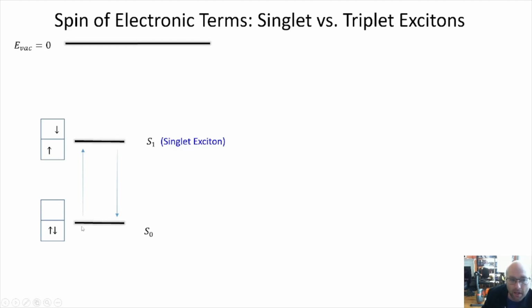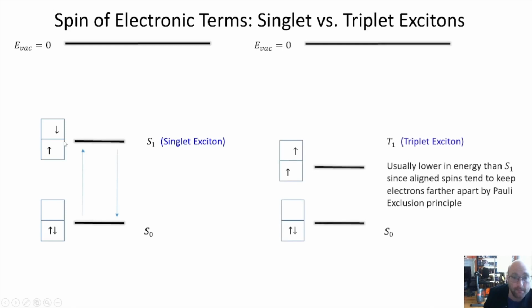And then when you absorb light, absorption itself is almost never going to flip a spin, right? And so you maintain spin 0 in the excited state upon absorption. And so singlet ground state goes to singlet excited state. Singlet just means S equals 0. So spin multiplicity equals 1 for S equals 0.